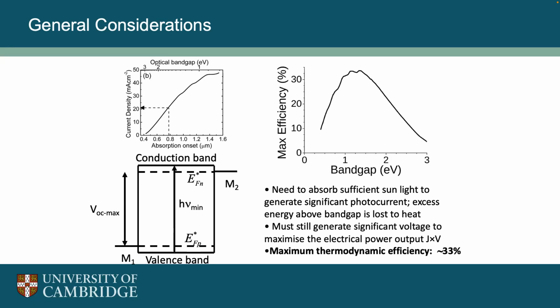So we need to maximize the products to get power. So what we end up having is an efficiency maximum at a particular band gap, which is somewhere about 1.1 eV, or up to 1.3 eV, depending on some of the calculations, which is actually not far off where silicon is. Silicon's a bit lower than that. And the maximum efficiency is about 33%.